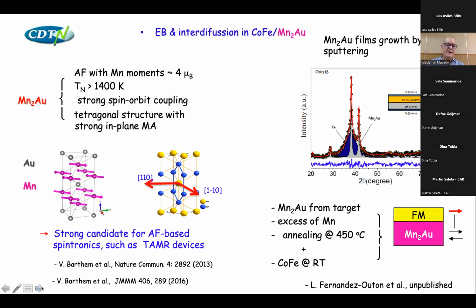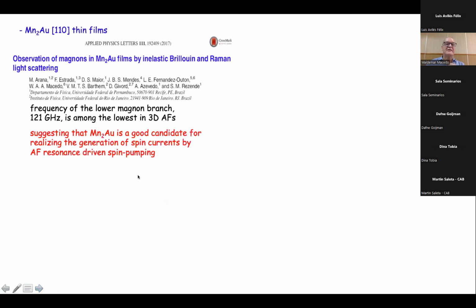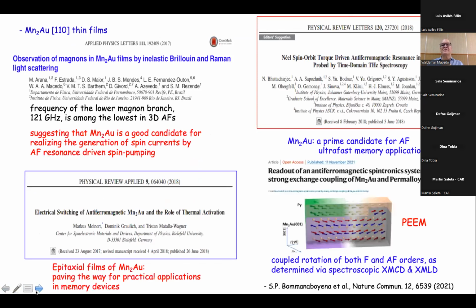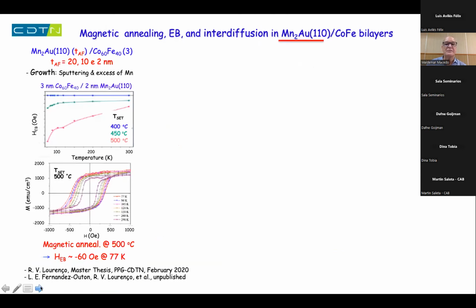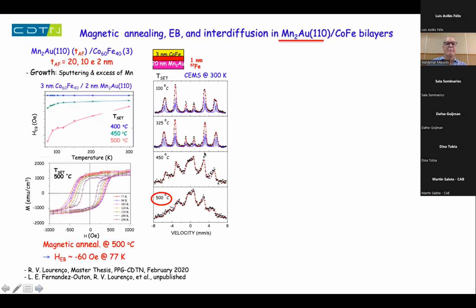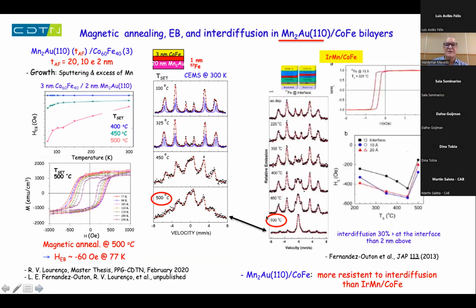bias in these systems. And though we did that, and these systems were used in these works, if you go to the literature, you see that manganese to gold is a very important material nowadays. And the only thing I want to show you today is that by doing the same experiments, putting a layer of iron 57 at the interface between cobalt to iron and manganese to gold, we see that this system is much more stable, is more resistant to the diffusion than iridium manganese cobalt.